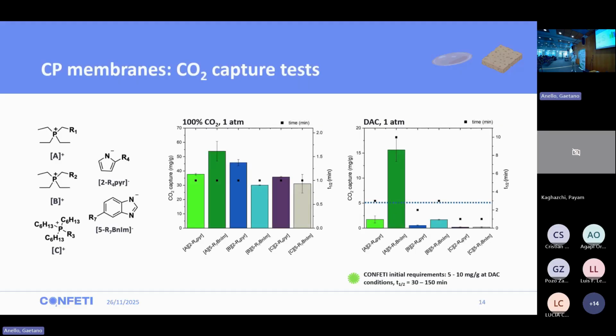When we tested these materials, we saw that in a 100% atmosphere of CO2, the capture was quite the same for all the ionic liquids, between 30 and 50 milligrams per gram. But for me, the most surprising of these results was the time of half saturation, that in all the cases is around 1 minute. So this fast kinetics suggests an excellent accessibility of the CO2 to the active sites of the ionic liquid.